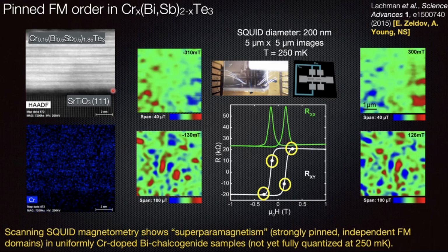And what Eli basically, I didn't like the term he used. He calls it superparamagnetism. I like to call it strongly pinned ferromagnetic domains. But what Eli showed was that, unlike all the magnetically doped semiconductors that we had been studying for years, which behave magnetically like good, well-behaved ferromagnets. How do they reverse the magnetization? Well, in a large sample, you get the propagation or expansion of domains. You get propagation of domain walls and expansion of domains.